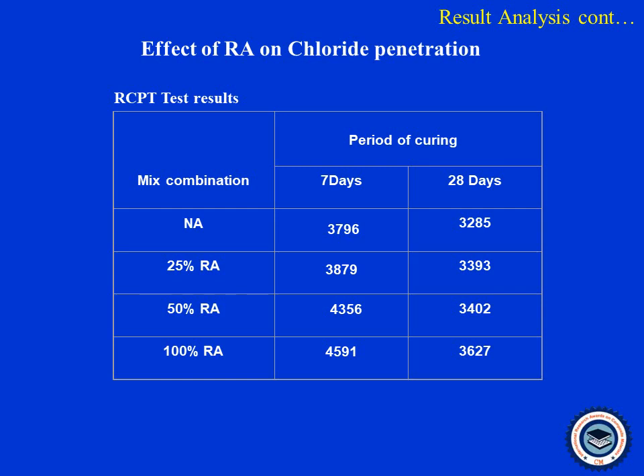From the results, it is understood that the total charge passed through the recycled aggregate concrete cylinder is greater than the natural aggregate concrete cylinder. So obviously the chloride permeability also increases with the increase in the percentage replacement of recycled aggregate. But everything is within the limit, because even for the 100% replacement we got only 3627 coulombs. That means it is in the permissible limit, and the chloride ion penetration permeability is in the moderate range as per the RCPT test.